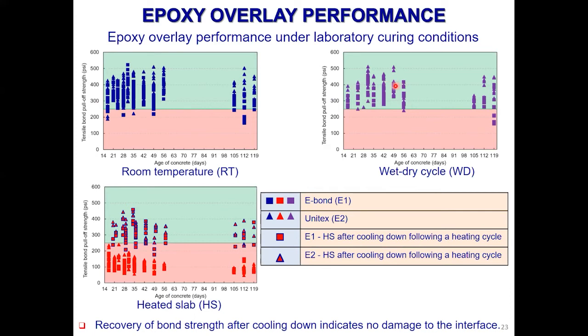Temperature is the biggest factor. When we heat the slab to about 110, 120 degrees, bond strength significantly decreases, and all the time we see bond strength less than 250. And then once we let it cool down, bond strength recovers. That means there's no permanent damage. So there should be some temporary damage or reduction in material behavior or strength with elevated temperature.